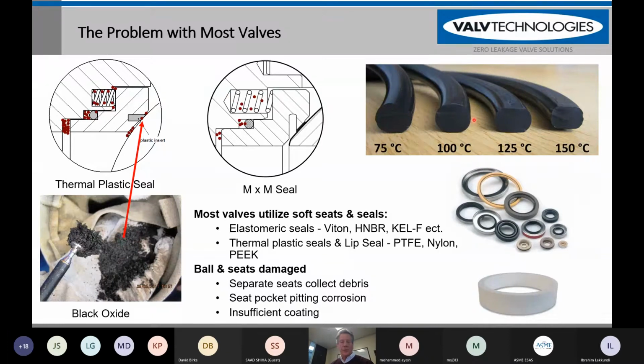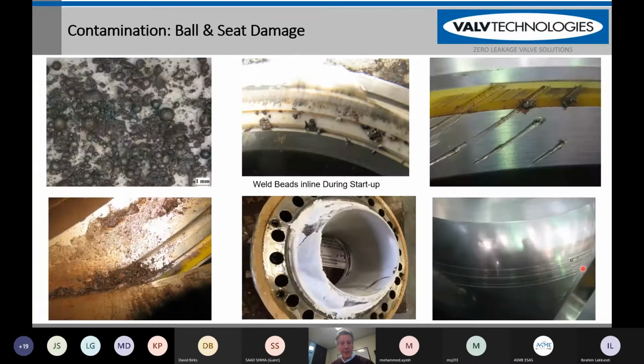Also, elastomeric seals, when they get into higher thermal cycling, you can see here that this is a Viton seal, and you can see how much it deforms as the temperature goes up to 150 degrees C. These are thermoplastic lip seals that, given the right working conditions, work outstandingly well, such as Chevron V packing right here. But again, when you start having severe service applications, all of these types of seals can be damaged.